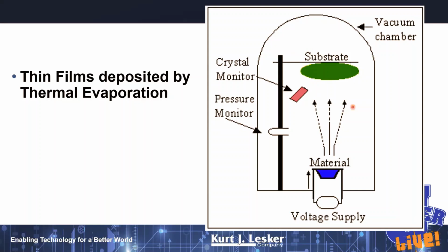going to develop here. This chamber, again, can be at the lowest possible pressure that you can achieve. So 10 to the minus 8 torr is not a bad number for a thermal or E-beam evaporation system. You do not need a process gas. And so the lower in pressure you can get this system, the more pristine the films you're going to make. So you'll have fewer gas inclusions, fewer stacking errors and things like that. So again, think clean, pristine, lowest possible pressure you can achieve.